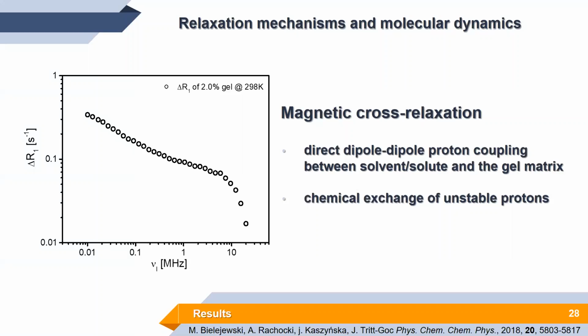The second reason is that there is a chemical exchange of unstable protons between the protons from the gel matrix and the protons from the diffusing molecule or ions. And this is also not the case, as the cations do not have exchangeable protons. So we ruled out this process.